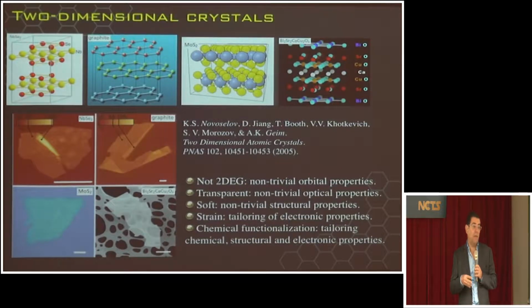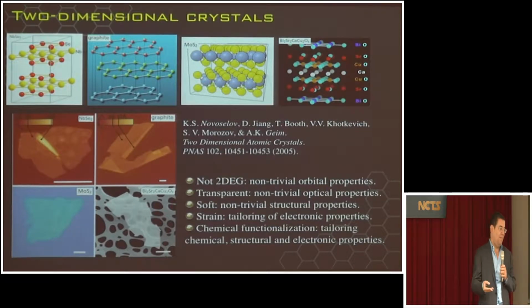And this has to do with the electron-electron interactions. Okay? So electron-electron interactions in graphene are very weak. The only thing they do is change the speed of propagation of the electrons, nothing else. But in these other materials, electron-electron interactions actually produce phase transitions. They produce new states, correlated states. And this is why they are more interesting from the physics perspective. And of course, much more challenging for the theorists. Okay?